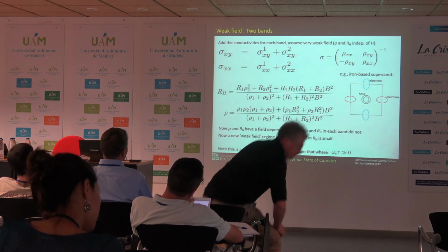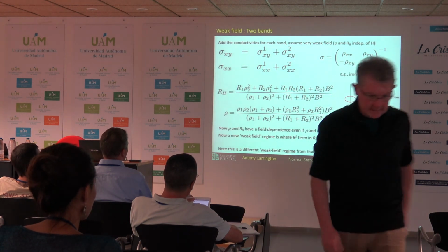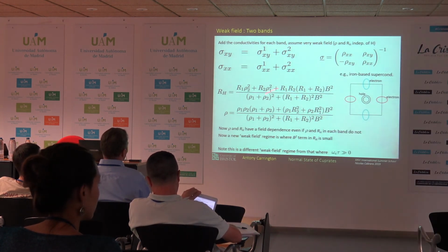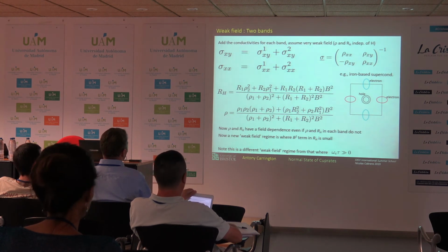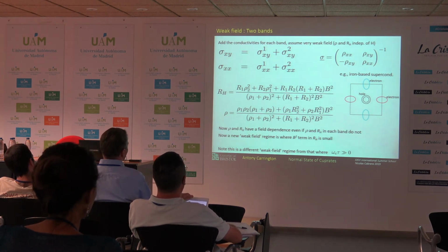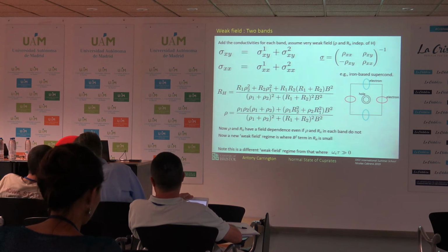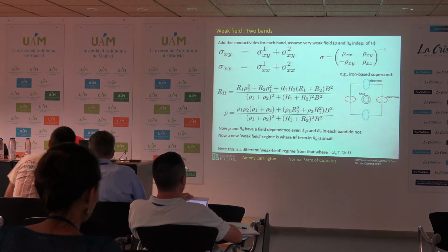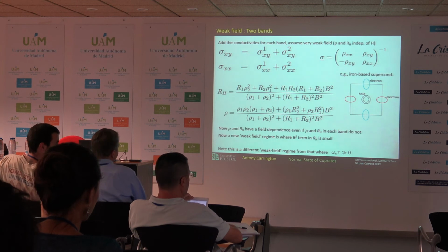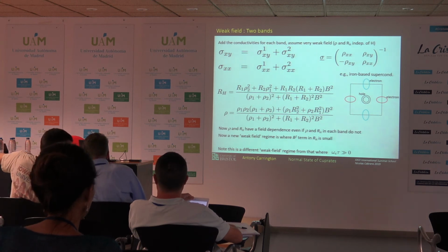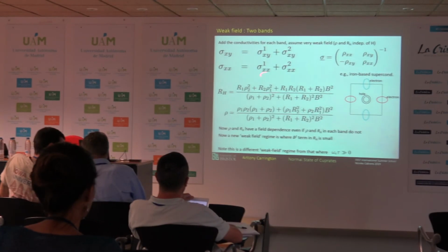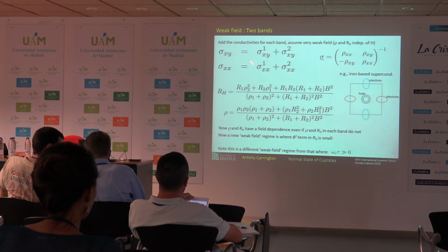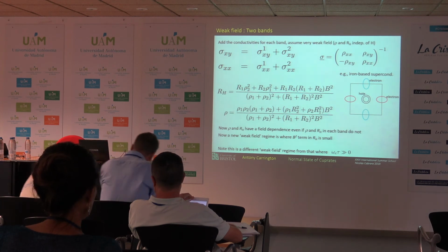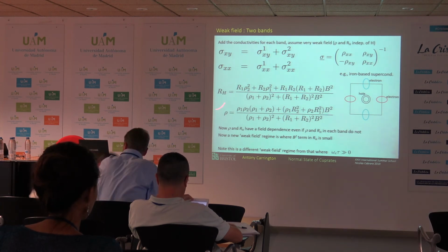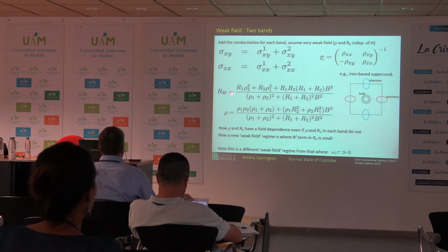Okay, so just for completeness. Since we're going to go in a minute to what happens in high field, I thought I'd just point out what happens when you've got two bands. So in cuprates, generally you've got one-band physics, but if you've got two bands, which you have to have in iron-based superconductors, for example, then what you have to do is to add the conductivities, both the Hall and the longitudinal, from the two different bands. So you add the conductivity tensors, and that gives rise to these rather complicated expressions for the Hall coefficient and the resistivity.